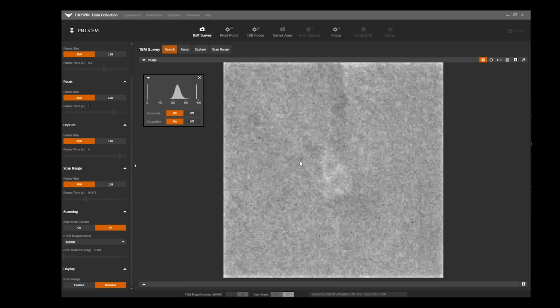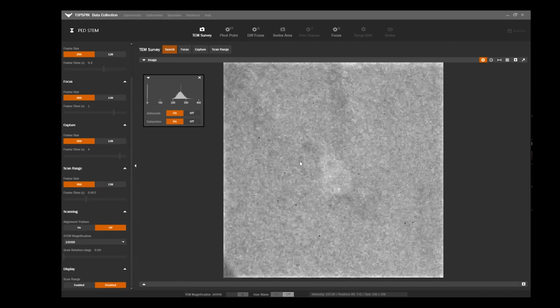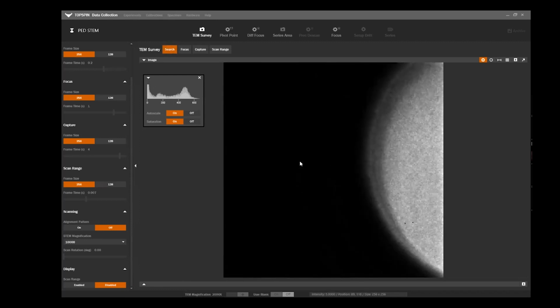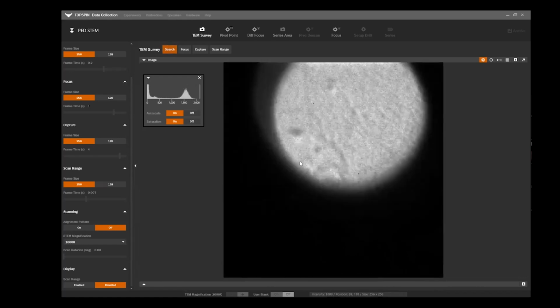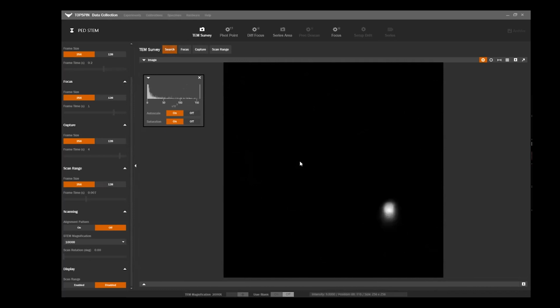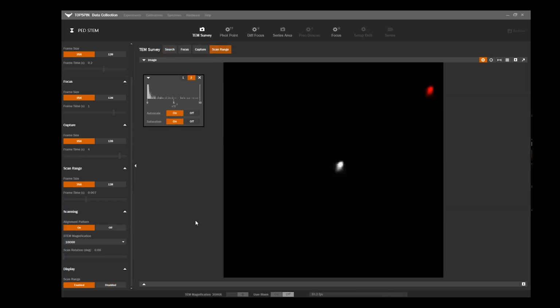And I will actually go ahead and just converge the beam to a spot. Because as Thanos explained earlier, we want to have a probe on the sample plane. Just a little. We want to have a probe on the sample. I actually forgot to take an overview image, which is not that important. Just go to the scan range here. And what we see right now is just a preview of the area that the beam will be rastering in a second. So basically I can acquire an image before and now have an overlay of where the probe will be rastering the sample. So with this, I'm actually quite happy.